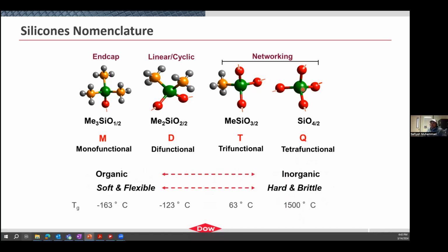So thinking about the properties of these monomers, and as we use them to form polymers. When you're down on this end with a high amount of M and D units, you have more organic nature because of the high presence of these organic groups on your polymer. And so these are often very soft and flexible materials. If you are familiar with the term PDMS, polydimethylsiloxane, that is made up of D units and can be capped with these M units here. So it's a soft, flexible material, often with a lower glass transition temperature.